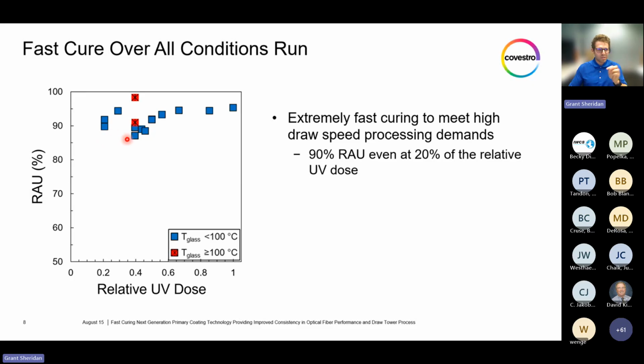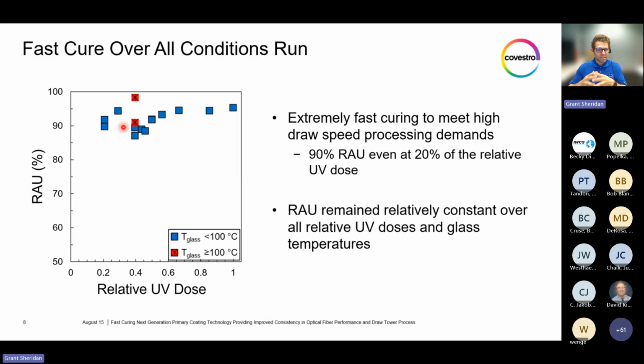Further demonstrating this extremely fast curing. Additionally, due to the extremely fast curing, the RAU remains relatively constant over all relative UV doses and glass temperatures, reaching 90% almost right away. It'd be very stable in terms of processing conditions if there are any variations, because there's not a lot left to cure at that point. So we believe that this extremely fast cure speed will lend well to the ever increasing draw tower speeds.